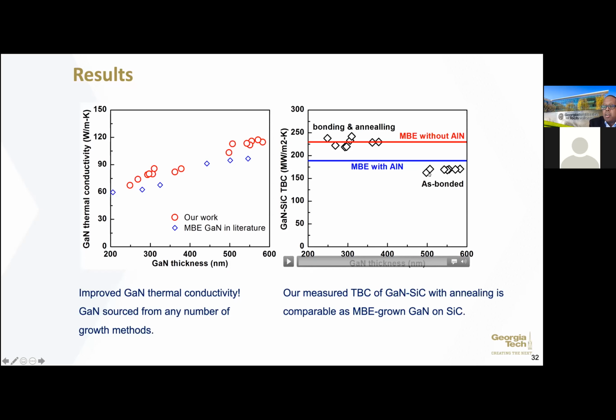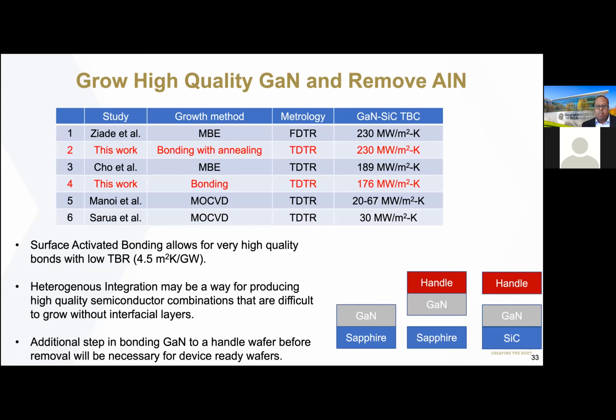If I look at the thermal resistance or the thermal boundary conductance between the GaN and the silicon carbide, it's lower than if I grew it with MBE on the aluminum nitride on top of silicon carbide. So I'm not doing any better here. But after I do the annealing, what you see is that we end up getting values that are very high, which are on the order of what you would see with MBE growth directly on silicon carbide in terms of that thermal boundary resistance. So this work, again, was from Z, who's currently a postdoc there in the Cahill group. And so you can see that this is one of the highest values that we've seen for thermal boundary conductance from gallium nitride to silicon carbide. But yet in this particular case, we do have the electronic grade material that could be used to make devices.